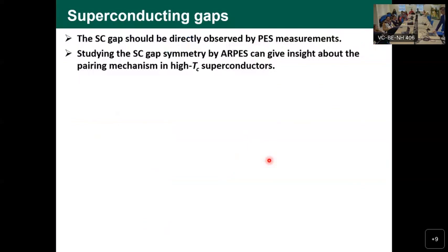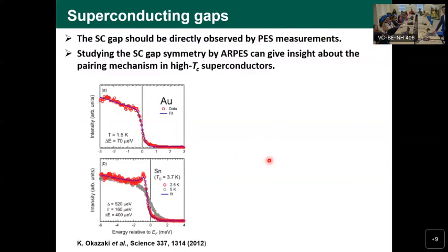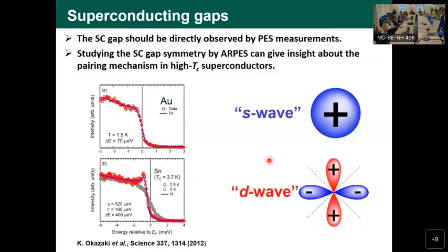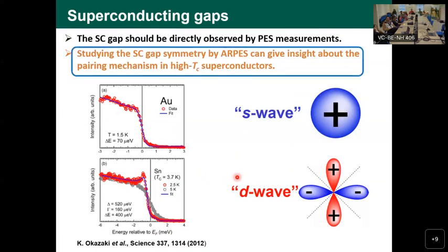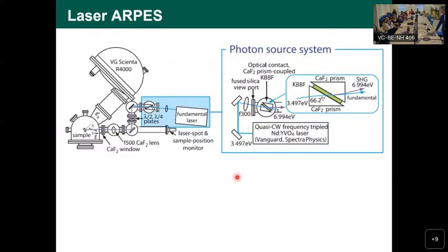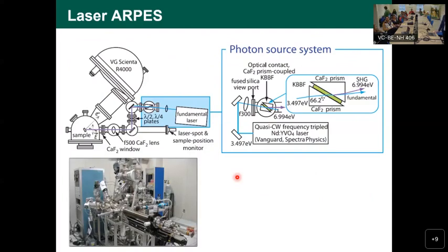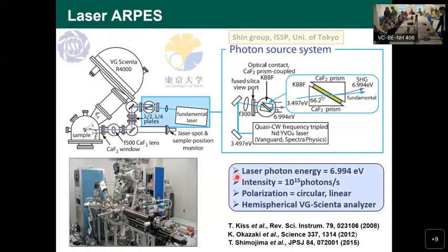And this superconducting gap can be observed experimentally by photoemission spectroscopy, as I show you here, a brief example. And we care about what we call the superconducting gap symmetry. Understanding how these electrons pair leads us to more understanding of the pairing mechanism, of superconductivity itself, and makes a kind of roadmap: what is the condition to get a high-TC superconductor? That's why understanding the gap symmetry is important, and this is what we did on the new iron-based superconductors using laser ARPES, with advanced lasers at the Institute for Solid State Physics at the University of Tokyo.